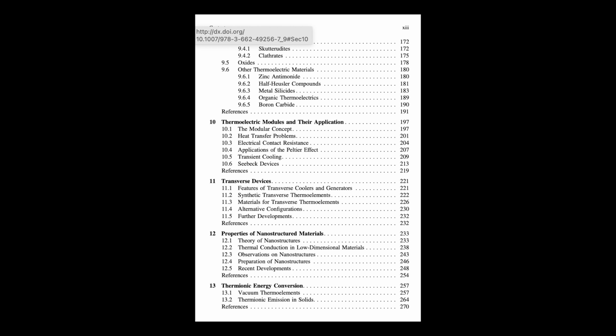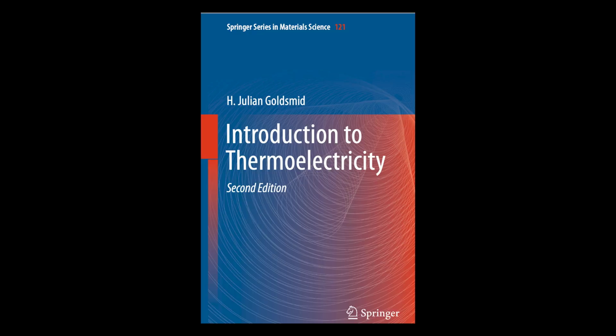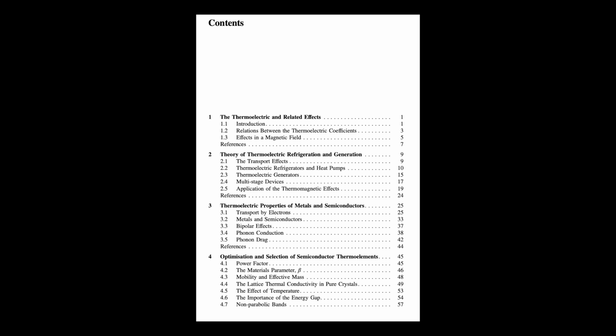Makes sense. And non-parabolic bands. We usually see nice, simple parabolas for energy bands. Reality check. Yeah, the simple parabolic band picture is an approximation, good near the band edges. But in reality, especially if the gap is small, or for carriers with higher energy, common in doped thermoelectrics, the relationship between energy and momentum gets more complicated. Non-parabolic. This makes the theory much harder. While we hope it's mostly the near-edge carriers doing the work, non-parabolicity might explain sometimes when simple theory doesn't quite match experiments.